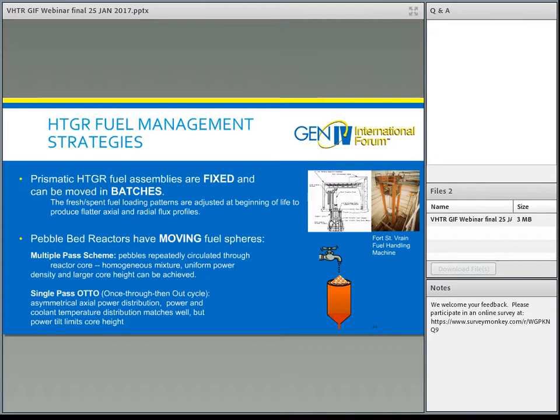In a pebble bed reactor, this more or less cartoon drawing shows how the pebbles come in at the top into the core barrel, and then over time they make their way down through the reactor. There are two ways of managing this. The first one is what's called the multiple pass scheme, where the pebbles come in from the top, move downward through the reactor, and then as they are taken out at the bottom, they are examined to see that they are still intact and not damaged in any way, and also to check how much fuel life is left in the pebble. If they can still be used, they can be taken back to the top and used over and over until the fuel inside has been expended.